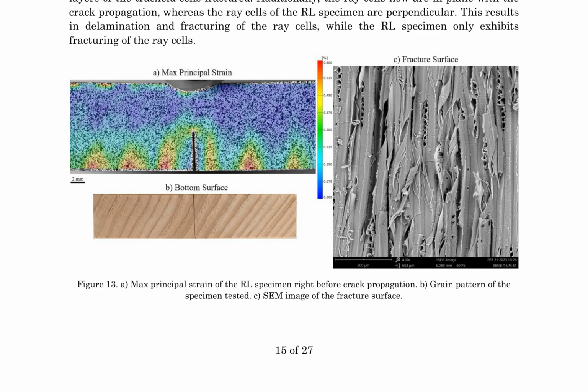This method allows for accurate determination of the fracture energy, even when the load does not soften down to zero. The use of this extrapolation technique is crucial for understanding the fracture behavior of quasibrittle materials like wood. The results highlight the importance of considering the orientation of ray cells in understanding the fracture behavior of wood. The findings also demonstrate the effectiveness of the exponential decay function in calculating fracture energies, which is essential for characterizing the fracture behavior of quasibrittle materials.